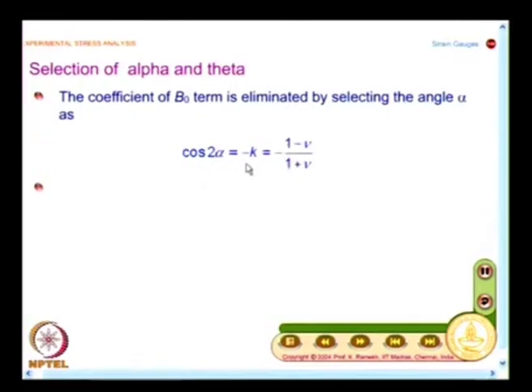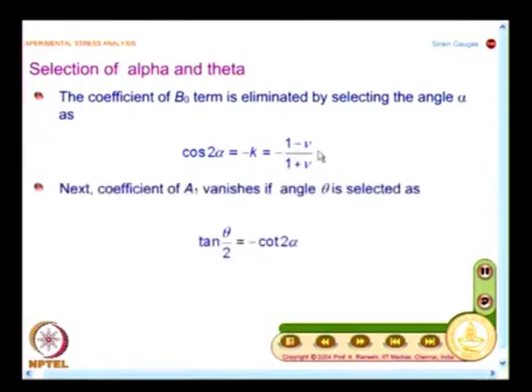So, we have cos 2 alpha equal to minus kappa, so you have minus of (1 minus nu) divided by (1 plus nu). So, I can find out what is the value of alpha, and if you look at the expression for A1, that vanishes if angle theta is selected such that tan theta by 2 equal to minus cot 2 alpha. See, you have the strain expression, and when you substitute these values of alpha and theta, you will find it is only a function of A naught, the terms containing B naught and A1 are cleverly knocked off.